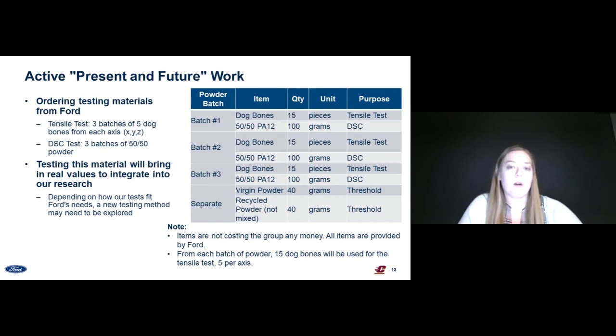Since Ford is going to keep their tensile test, we recommend that they keep it. It is a beneficial test for the testing of the polymer, and it is also low cost. So we're going to be running tensile tests on CMU's campus in order to compare our values with Ford's values, and make sure we know what we're testing, what parameters we're testing, and make sure our numbers are cohesive with theirs.